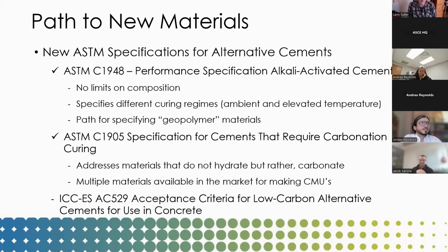In terms of cements, we've developed a new specification for alkali activated cements, C1948. This addresses cements that people commonly refer to as geopolymers, although I don't know if there really is such a thing as a geopolymer, but that term is used. But it's alkali activated. It's not a hydraulic cement. We now have a specification to address those cements. And those are typically used under different curing regimes, and so the specification addresses that.